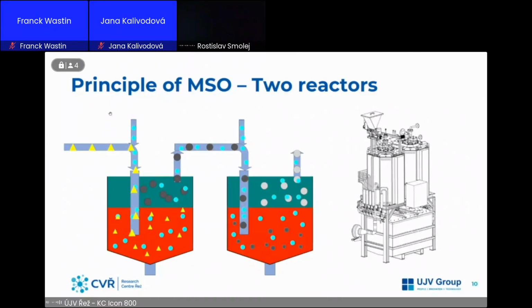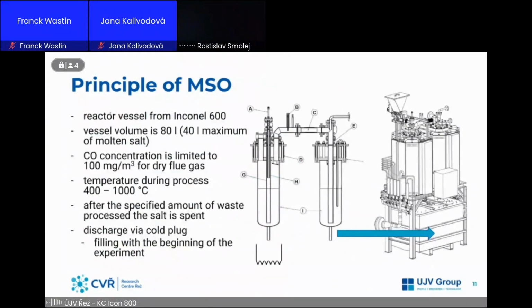It's a diagram. And a bit more data about the molten salt oxidation. We have the reactor vessels made from Inconel 600. It was very affordable at the time, and it offers really good oxidation protection from the salt melt. Also, each vessel volume is 80 liters. It could be filled up to 40 liters maximum with the molten salt. And for the standardized waste, we can get only 100 milligrams per cubic meter for dry flue gas, which is very good. But it is also for the standardized waste, which needs to be properly introduced in the laboratory and a few tests. You know how this goes.